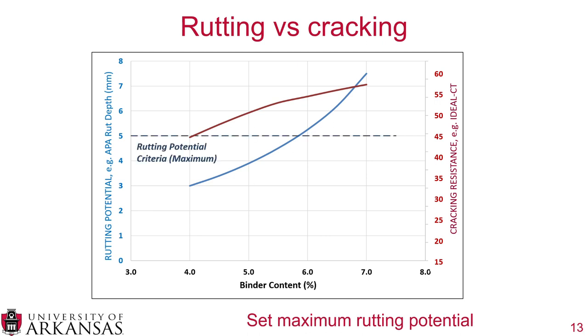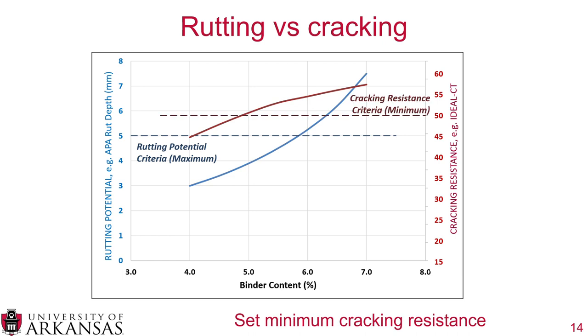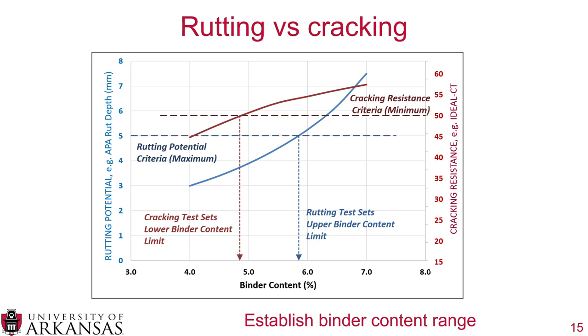So you have some sort of maximum rutting potential you want. Here I'm just saying a 5 millimeter rut depth is the maximum. And then you have some sort of minimum cracking resistance, and this happens to be 50 for the ideal CT. And what you can do is you can drop these lines down. The cracking test sets the lower binder content limit, and the rutting test sets the upper binder content limit. And what you do here is you establish a binder content range. If you want to balance rutting versus cracking, there's some range of acceptable binder contents. If you go below this range, you're going to be susceptible to cracking in theory. If you go above this range, you're going to be susceptible to rutting in theory.